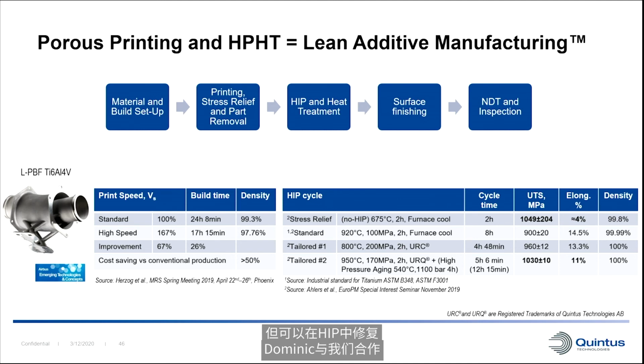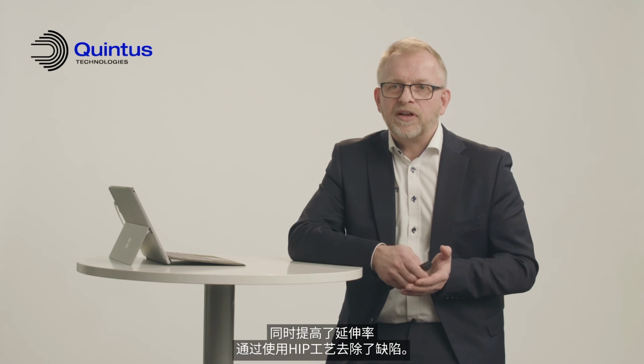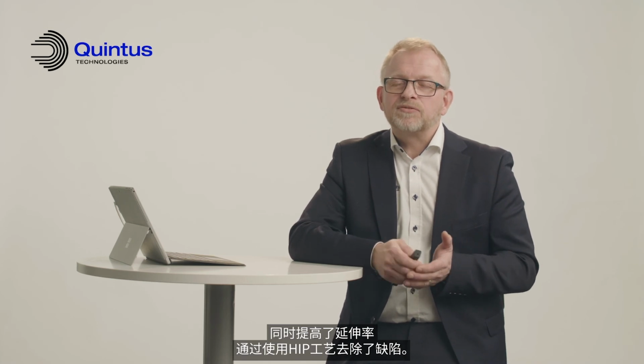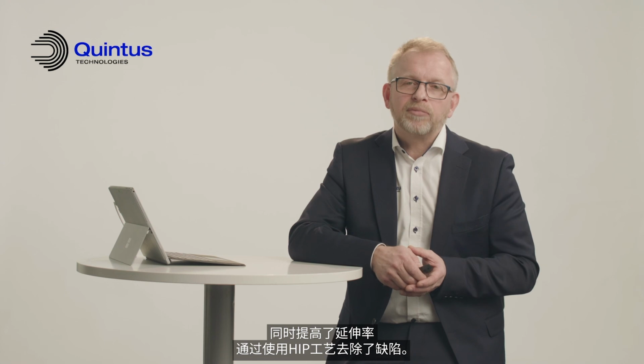And using the tailored cycles that Dominic has been working with us on, we've been able to get up the strength of the parts to the same level as the as-built material, but with extremely improved elongation results. So the tailored 1 and tailored 2 cycles here give extremely good results with higher strength and also improved elongation, at the same time as removing defects using the HIP process.